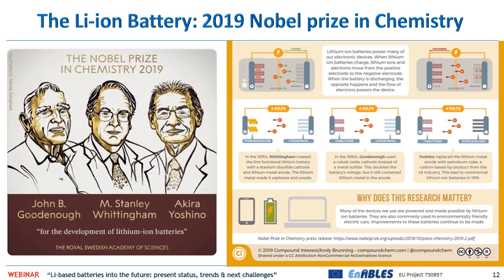As the battery discharges, the ions migrate from the graphite electrode to the cobalt oxide electrode, from right to left. When it's fully discharged, all the lithium ions have moved over to the cobalt oxide electrode, the cathode, on the left. Once again, the lithium ions sit in layers, in between layers of cobalt ions in red and oxide ions. As the battery charges and discharges, the lithium ions shunt back and forth from one electrode to the other.